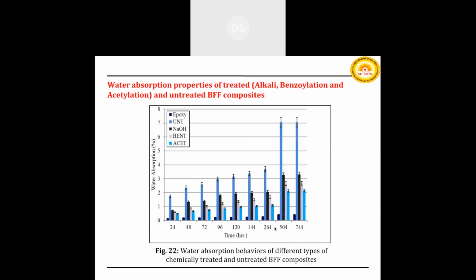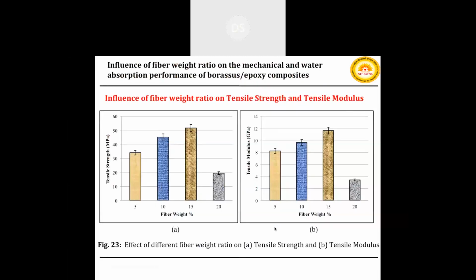Water absorption properties of treated, based on the alkaline, benzoylation and the acetylation, and untreated Borassus fruit fiber. I have already discussed this, and in all the chemically treated fibers, acetylation treated Borassus fruit fiber based composite shows the minimum 2% water absorption, followed by the benzoylation at approximately 2 to 3%, and alkali treated Borassus fruit fiber composite is 3 to 4 percent. Okay.